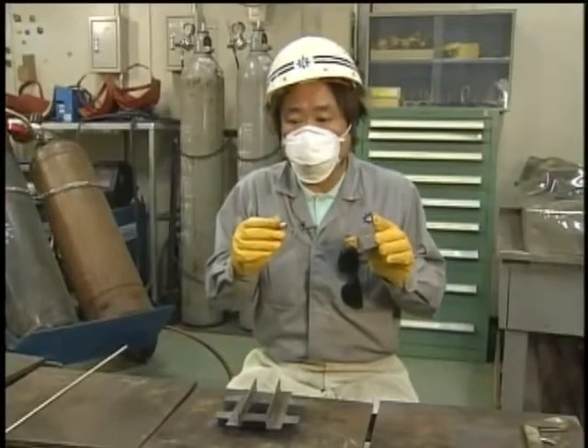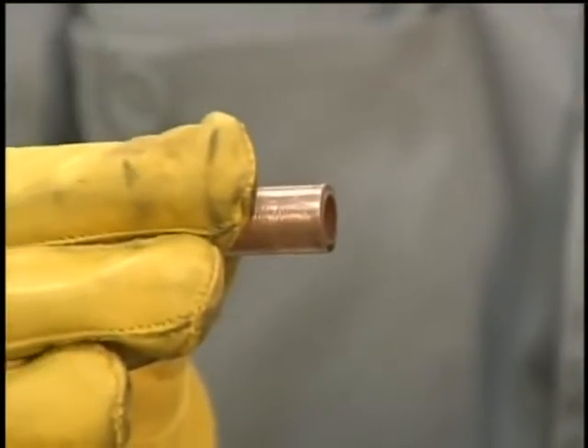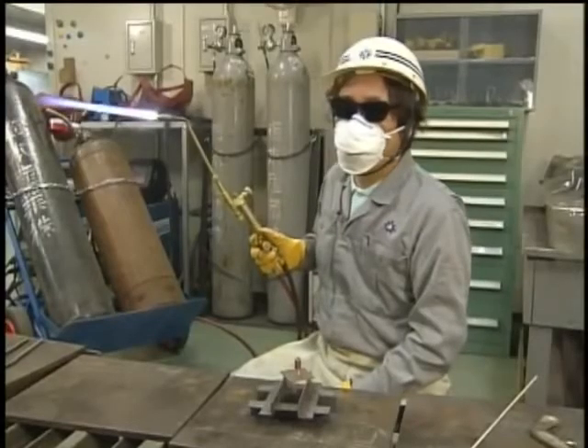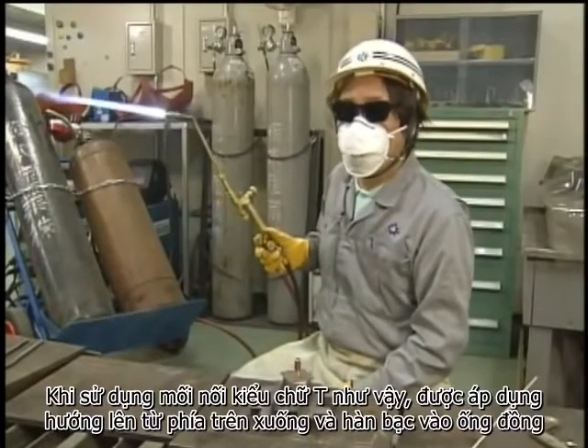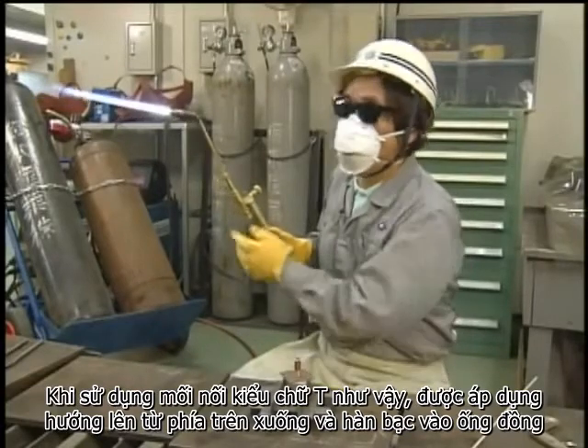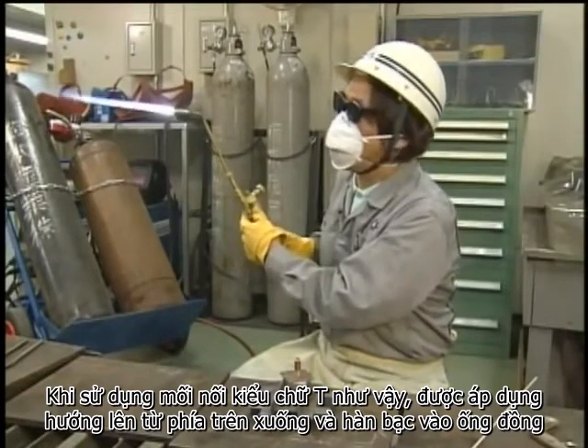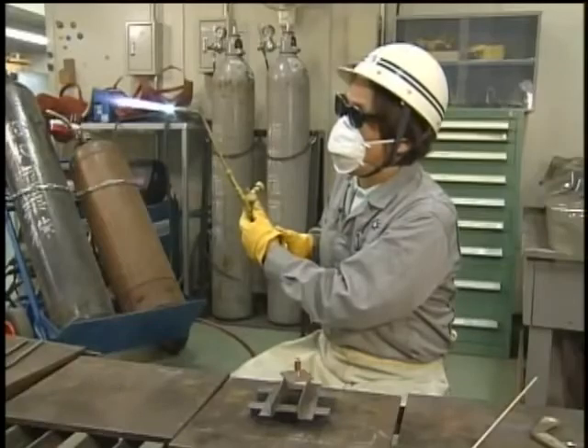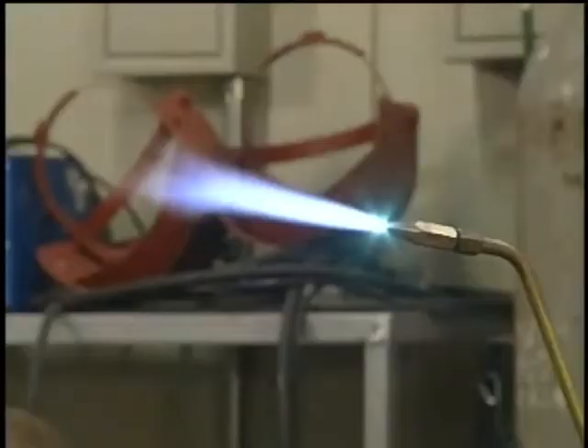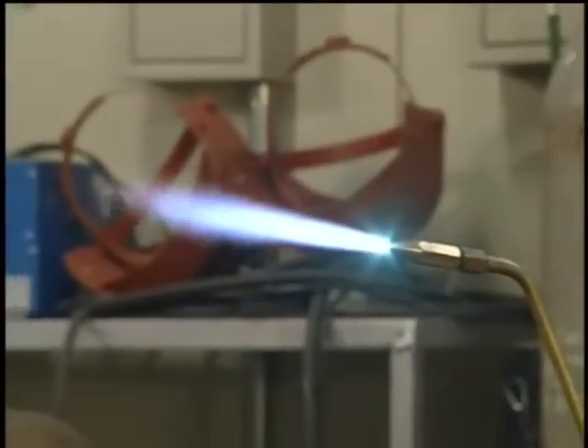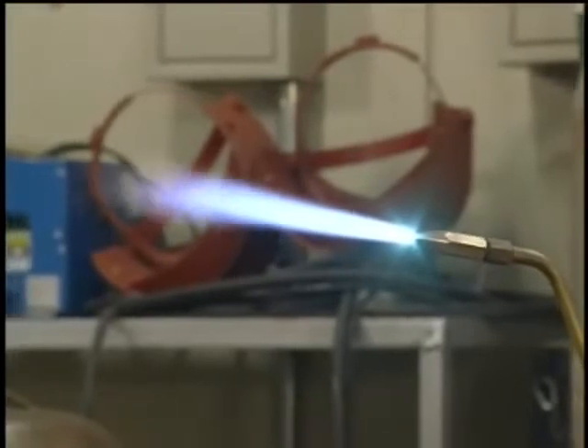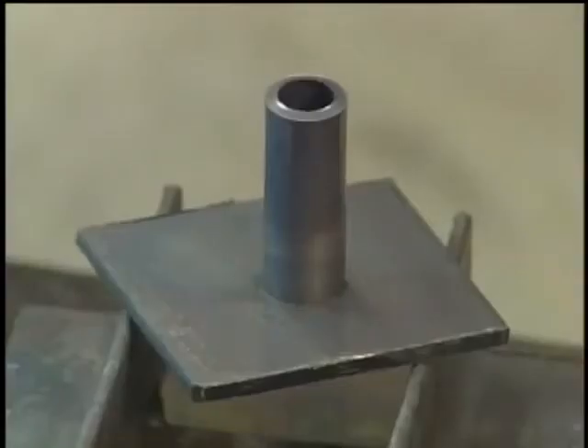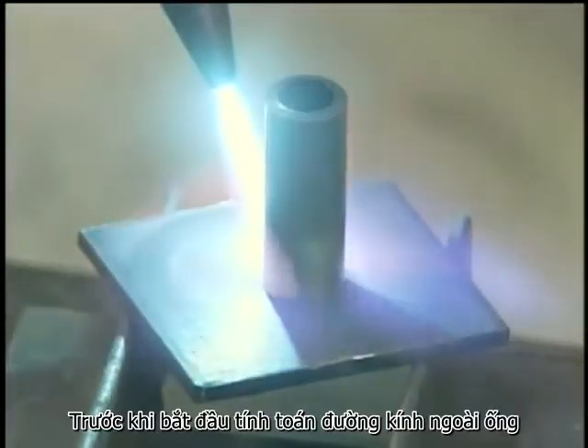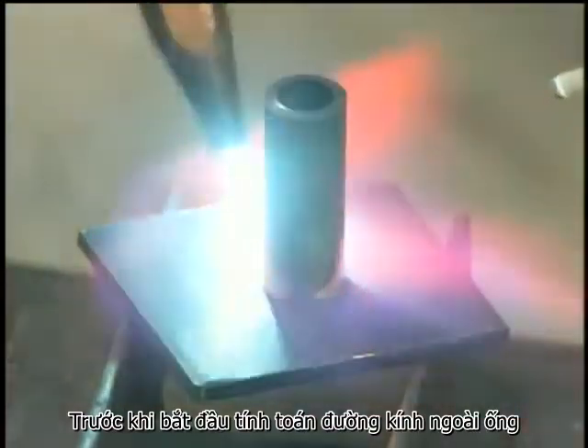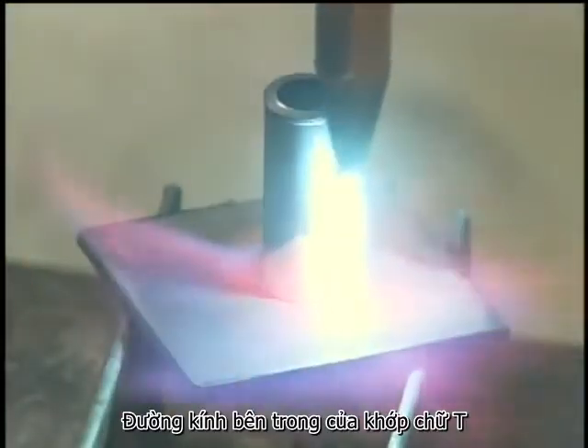Use a brass rod to solder mild steel plate and copper pipe. Because soldering does not involve melting the base metal, you don't need to make a neutral flame as for welding mild steel plate. A little excess acetylene flame or carbonization is no problem. When applying the flame, be sure to heat the two metals uniformly so as not to melt the base metal.